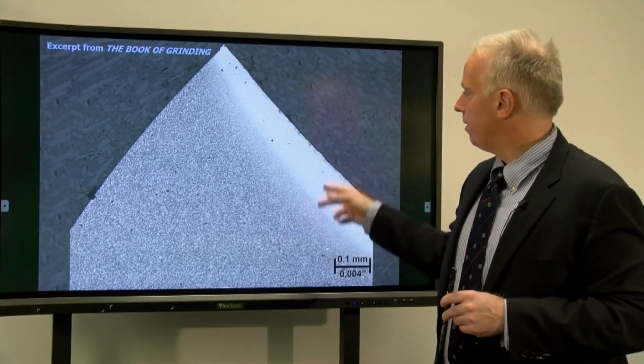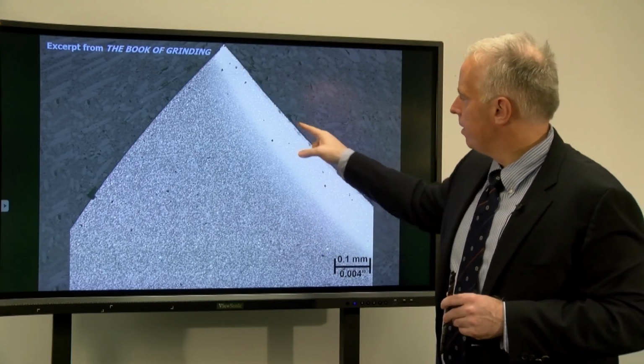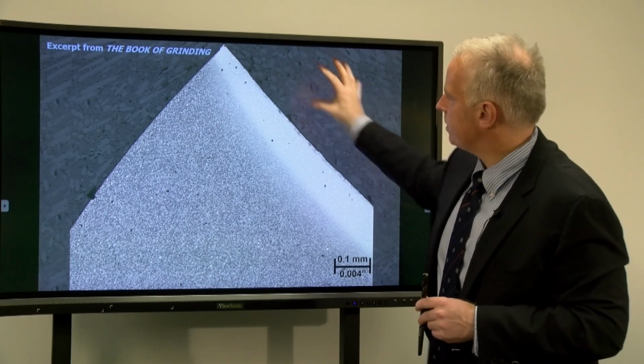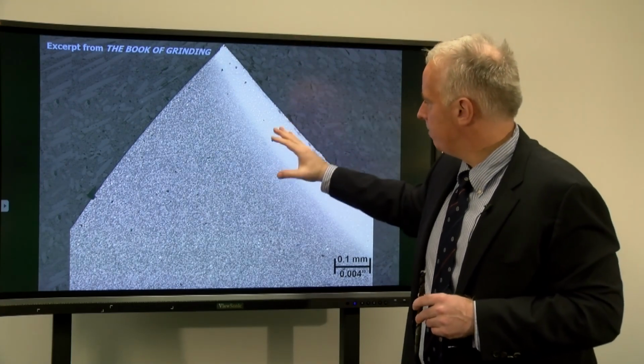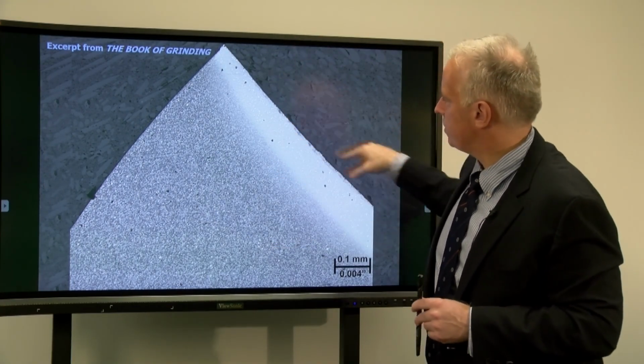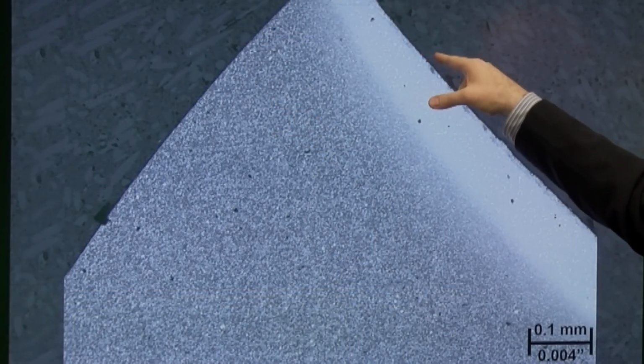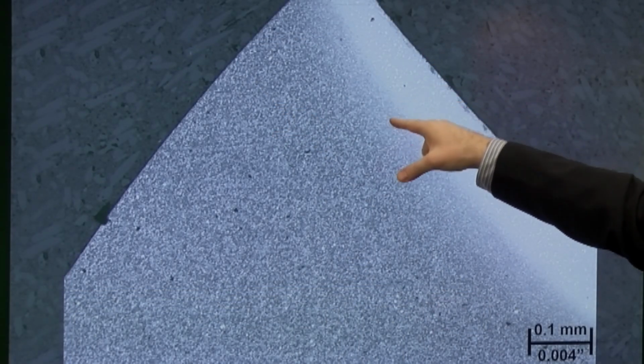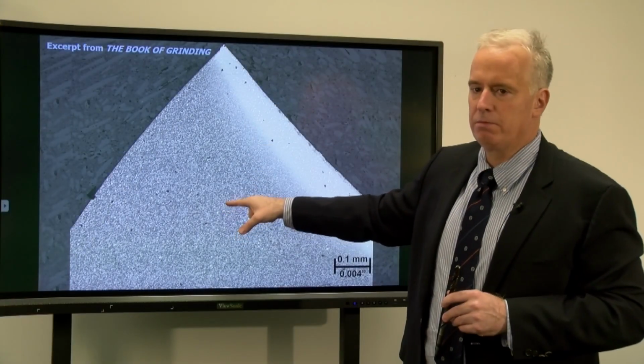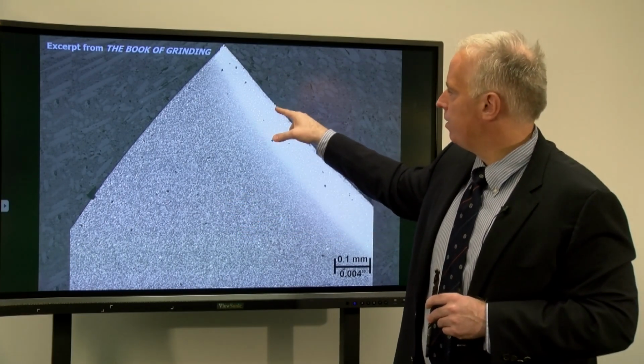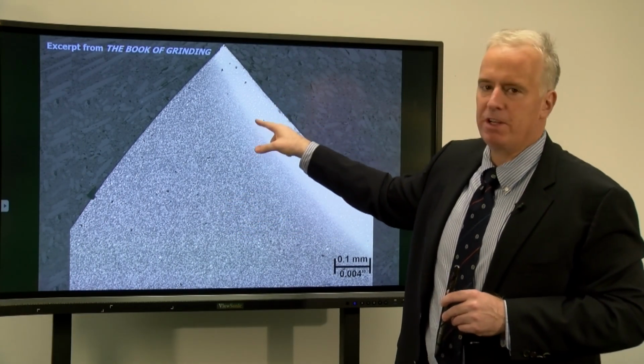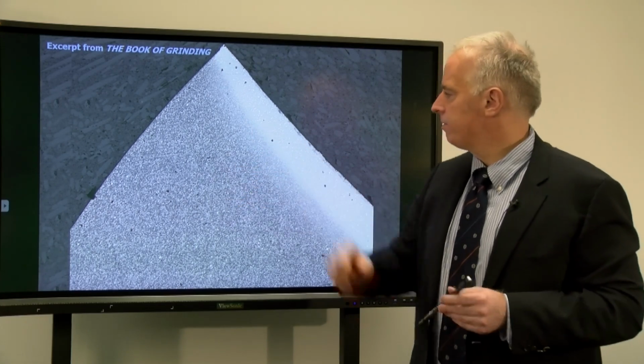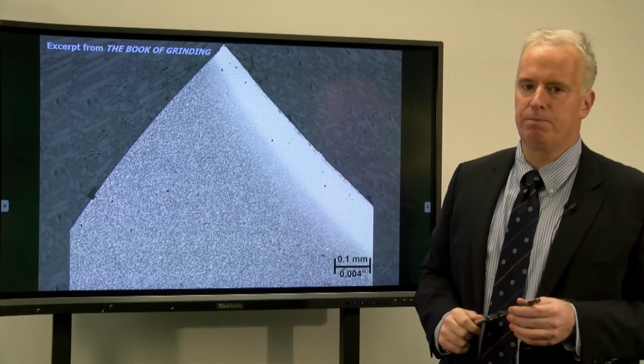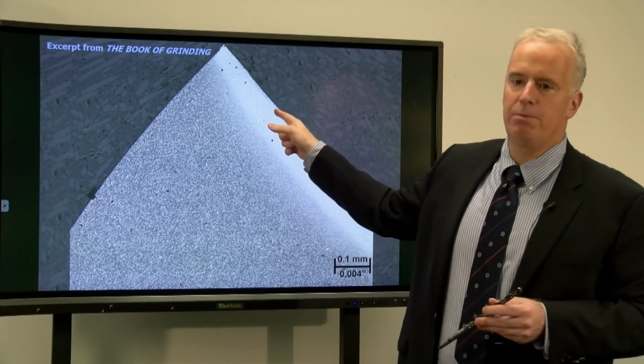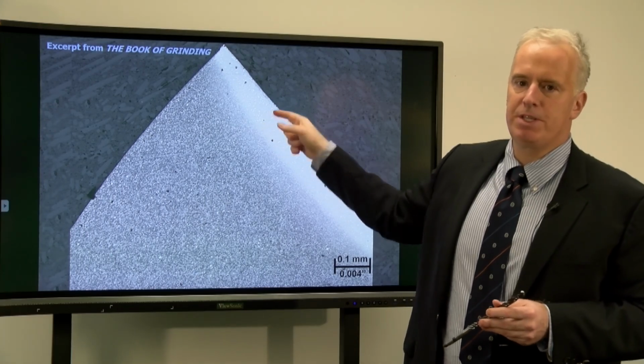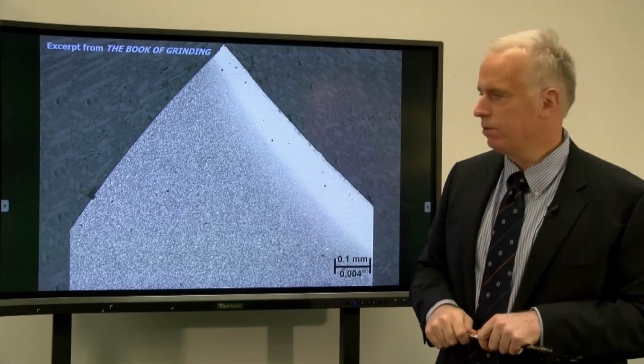And here's a picture of the white layer. So this is the ground surface. And then here's the workpiece. This is the ground surface. Temperatures got super hot here, pretty hot here, not quite as hot here, sort of hot, and not too hot. So what we have is rehardening burn, a little bit of softening here, and then we have unchanged material. Okay, now this material is hard and brittle. So what happens if we put this material under cyclic loading?